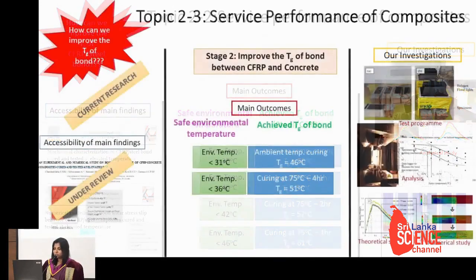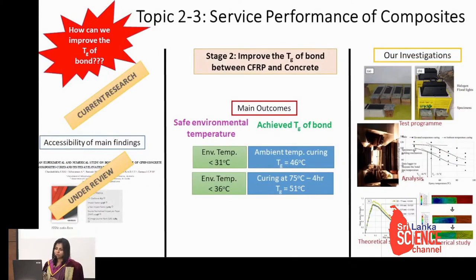Initially we did laboratory testing and found it works. But the next question is, how can we give similar conditions in practice? Otherwise our findings are useless because our structures are large. So we have seen that in cold countries, they used a halogen light system to elevate the temperature in structures. So we tried to develop the same concept for our applications. We designed a series of halogen lighting systems to elevate the temperature near the strengthened member. And this is practically feasible, and it works. Finally, after analytical and numerical simulations together with the experimental program, we could find the correlation between safe environmental temperature, Tg of bond, and possible elevated temperature curing. So this works well for the Tg of the CFRP and steel bond.